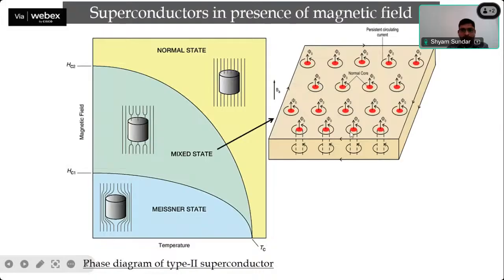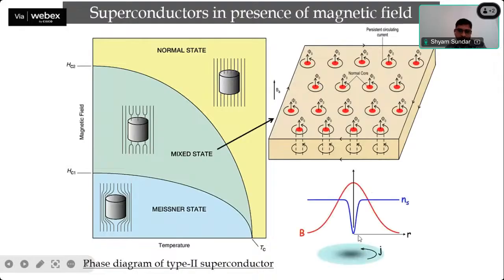And they have a very well-defined form, usually a hexagonal pattern, a hexagonal lattice. And if you want to see the structure of a single vortex, this is the structure of the single vortex. Around the periphery you have this supercurrent, and because of the supercurrent you have the magnetic field maximum in the middle, at the core of the vortex. But as you go away from this core, your magnetic field starts decreasing.